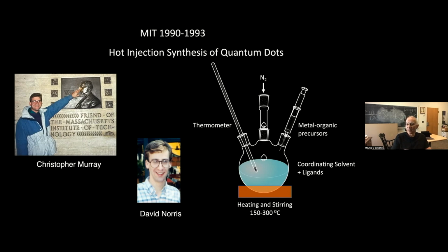And so we developed this process by which we inject very quickly these metal organic precursors in a hot solvent. They reach the hot solvent, they decompose, and they begin to react to form these little seeds. The temperature goes down, the concentration of the precursors goes down, and the seeds stop forming.